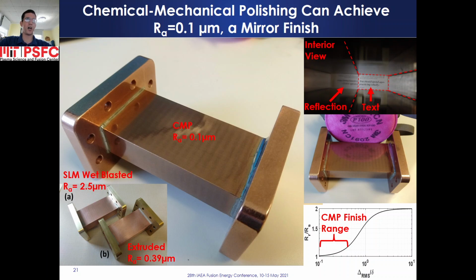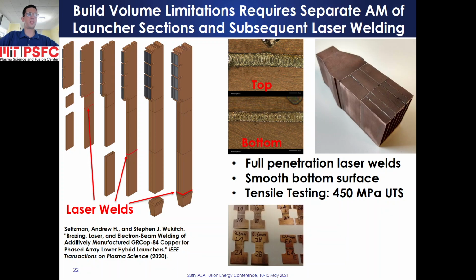extruded oxygen-free copper waveguide. Build volume limitations required separate additive manufacturing of launcher sections and subsequent laser welding to join sections together. Unlike many copper alloys, GRCop-84 has excellent laser welding properties due to good coupling with neodymium YAG and fiber lasers. Top and bottom of full penetration weld beads are smooth with minimal spatter when welded under an argon or argon-helium inert atmosphere. Butt welds on 0.3 to 1 mm thick GRCop-84 coupons maintained a 450 megapascal ultimate tensile strength, as the rapid melting and resolidification during pulsed laser welding resulted in minimal modification of the precipitate structure.